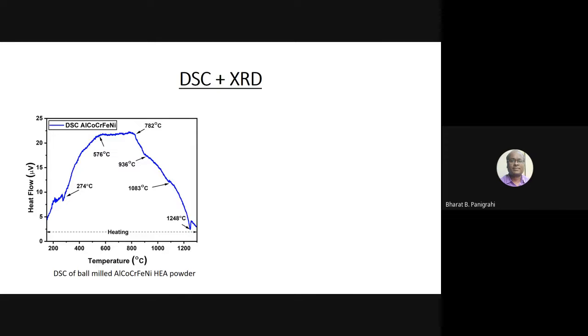Exchange of heat. Any chemical reaction or phase transformation involves exchange of heat, either heat release, which we call an exothermic reaction, or heat absorbed, which we call an endothermic reaction. So at whichever temperature this heat exchange is happening, either absorption or release can be accurately detected using the instrument called DSC, right? So this we can see here, the DSC profile as a function of temperature of the mechanically milled powder. The alloy has been prepared.